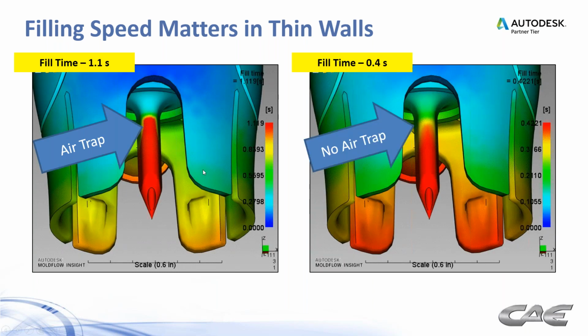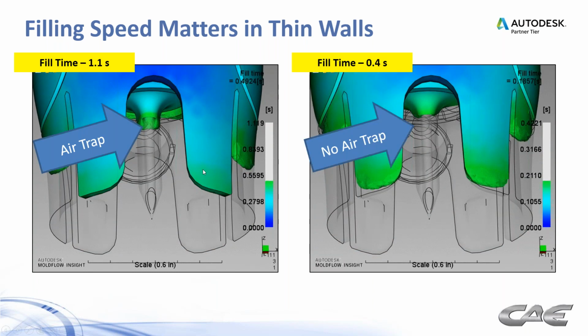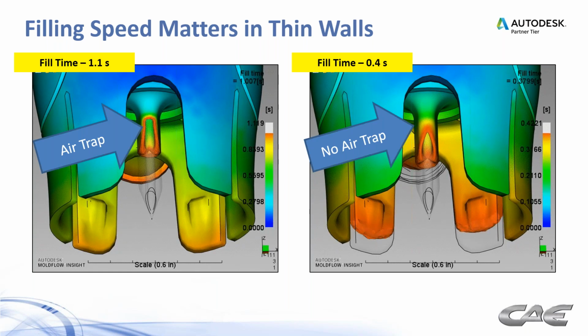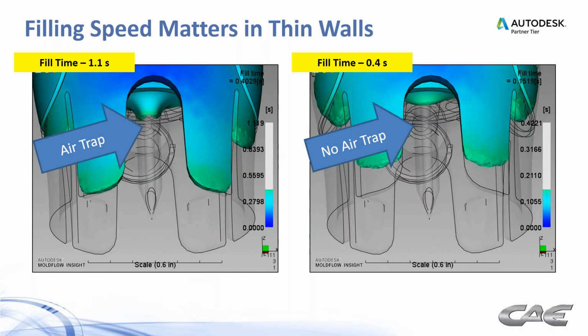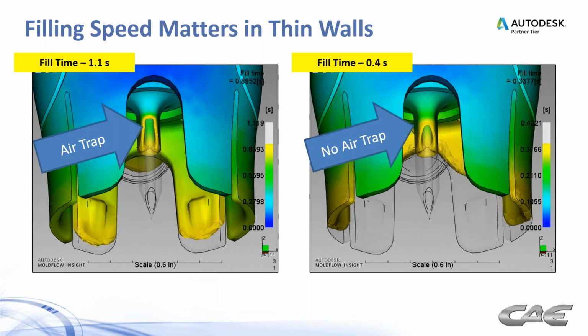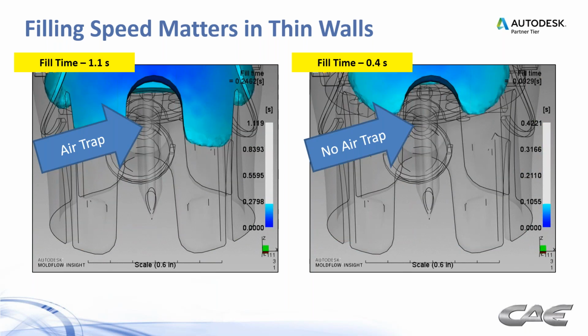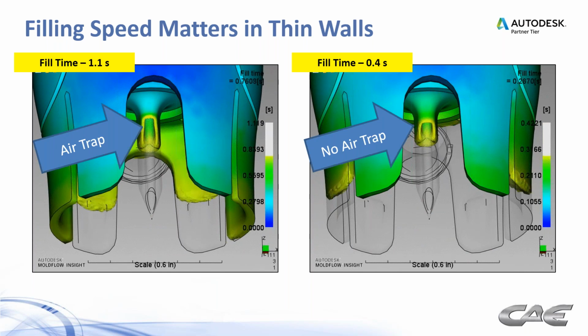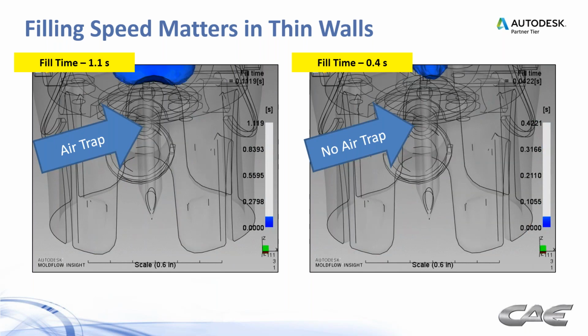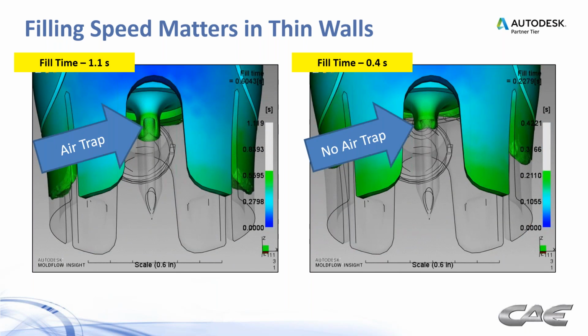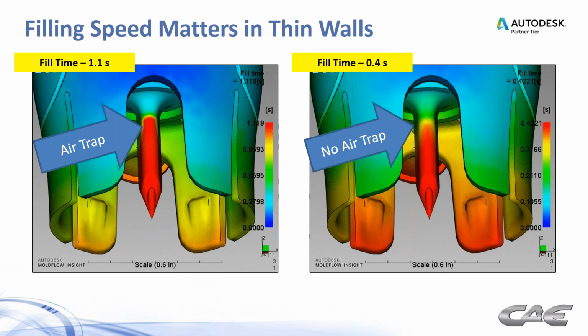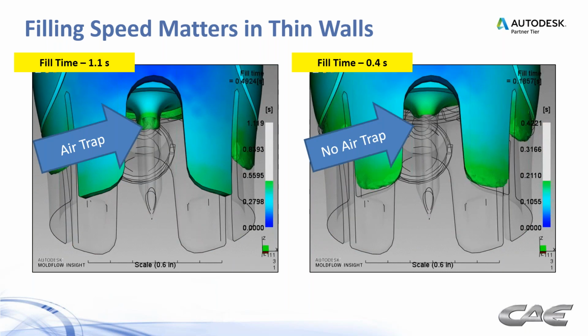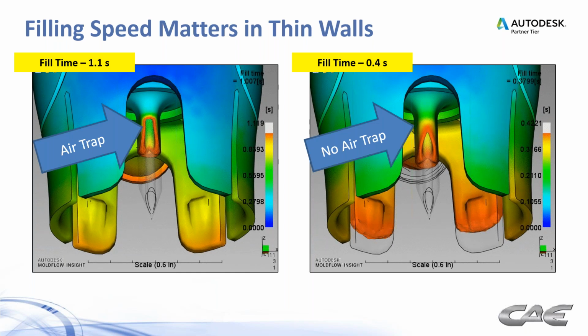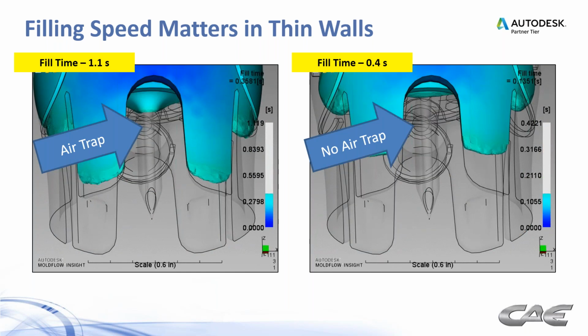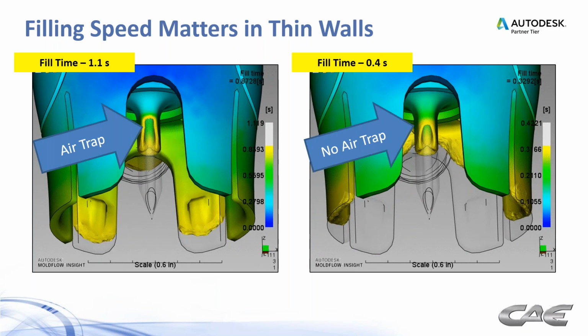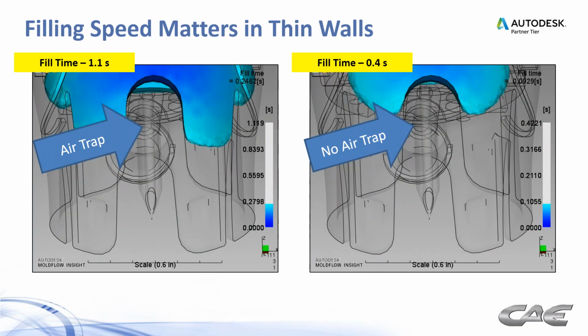You'll see here in a second that with that thin wall, oftentimes you can get into a situation where you have an air trap. And this is kind of a thick wall versus thin wall deal, where plastic wants to go into the thicker walls, and meanwhile it hesitates as it goes into the thin wall. So what you end up with oftentimes is a backfilling condition, as they were seeing here, and also a knit line situation, which can compromise the integrity of the part.